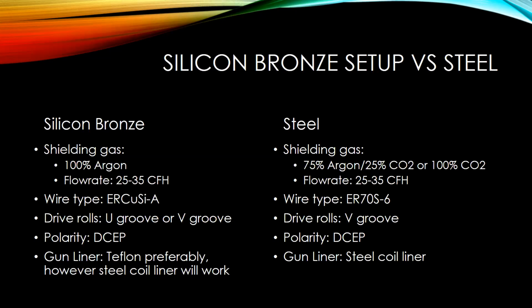So over on the left, the common shielding gas that's used with silicon bronze is 100% argon. Typical flow rate will be between 25 and 35 cubic feet per hour. The wire type is an ERCuSi-A, and that might vary dependent on the manufacturer. Some good drive rolls to use would be either U-groove or V-groove. The polarity, direct current electrode positive, and a good liner to use is Teflon.